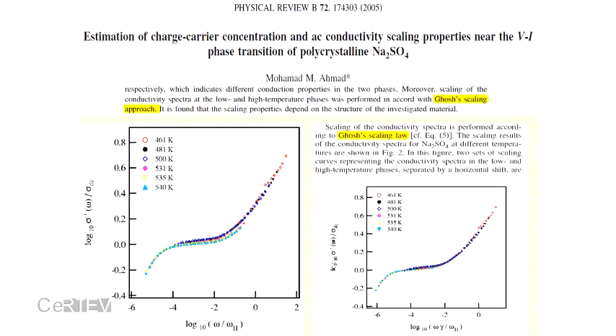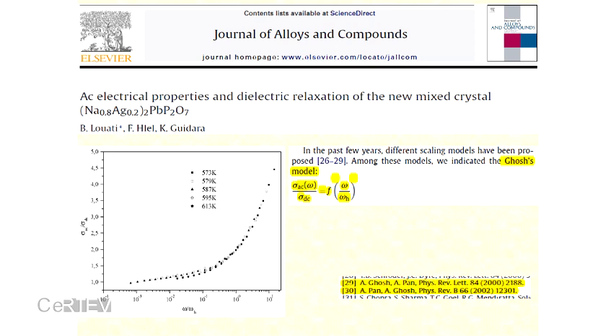Here I have shown results from a study of the phase transition of polycrystalline materials. Before the transition they have one type of superposition, and after the transition they have another, because the transition depends on temperature. Some authors are plotting this way and predicting that there is a transition at this point. They have also plotted like this in crystalline materials, mixed crystals. They have tried to understand the conductivity spectra using Ghosh's model and dynamics.